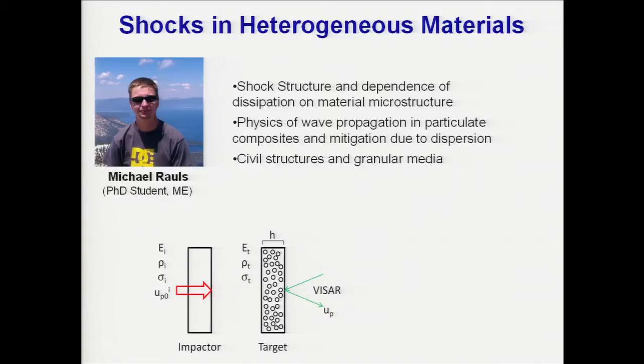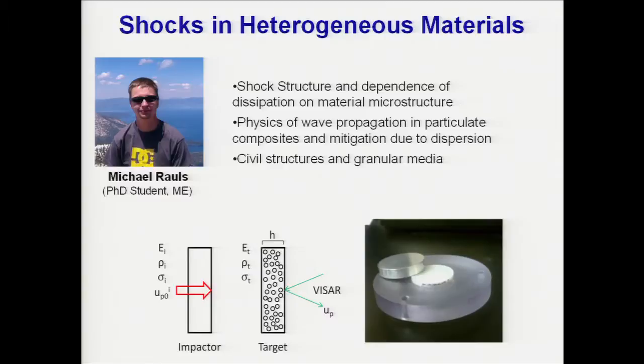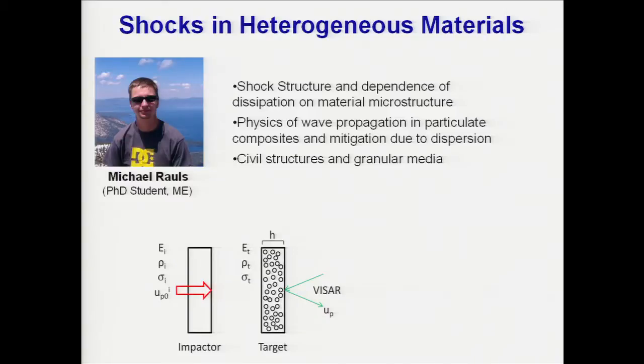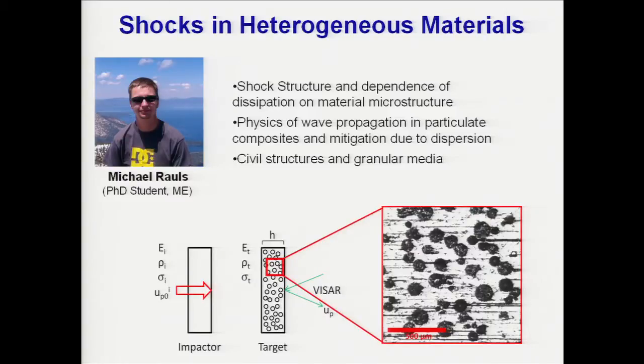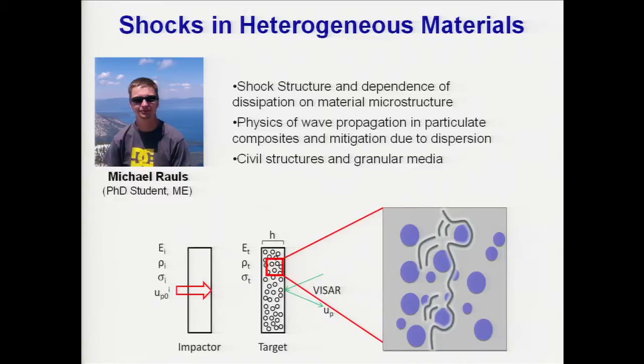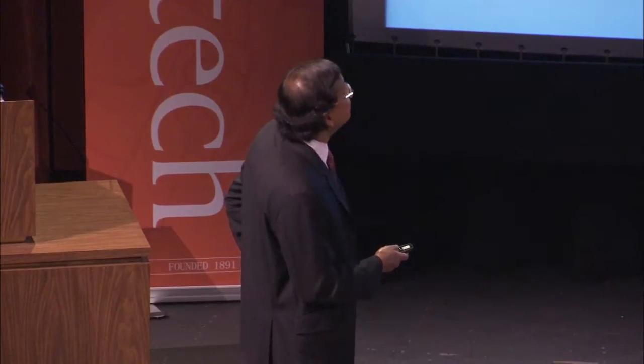In this case, you want to think about particulate media. So he's making particulate composites. He's using a model composite, plexiglass embedded with glass spheres, and it's being impacted by an aluminum impactor. If you look at the microstructure of this material at a very small scale, about half a millimeter, you see glass spheres embedded in the plexiglass. The idea is really to disperse this wave. As the wave propagates through such a microstructure, you can cause dispersion and dissipation of the shock through the material. We are investigating these concepts, and Mike is working on this project.